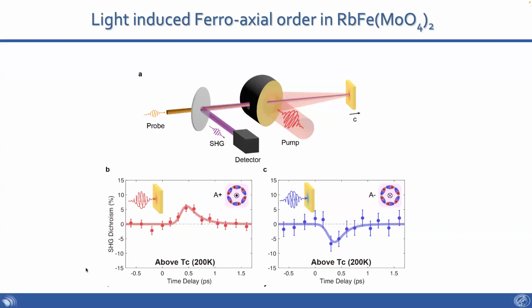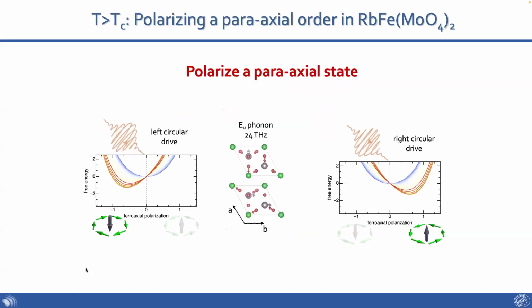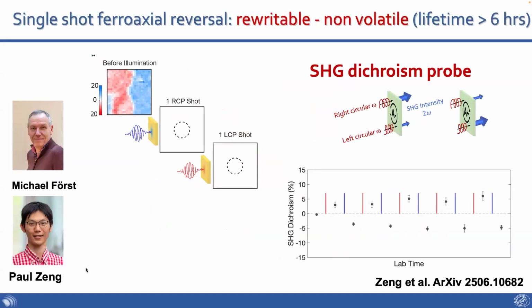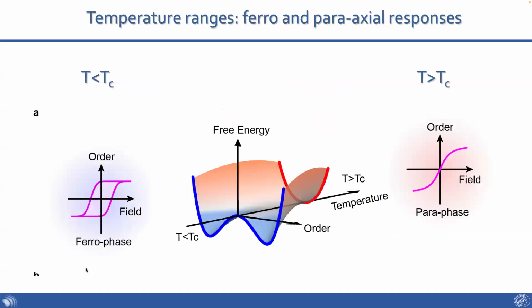Have you investigated how this relaxation changes as you approach TC from above? What we have investigated is the threshold as a function of temperature. We're trying to find some form of photosusceptibility of this effect, and that seems to almost diverge, right? But not in enough detail. It's on the archive, so if you're interested, you should take a look at the data. Okay.